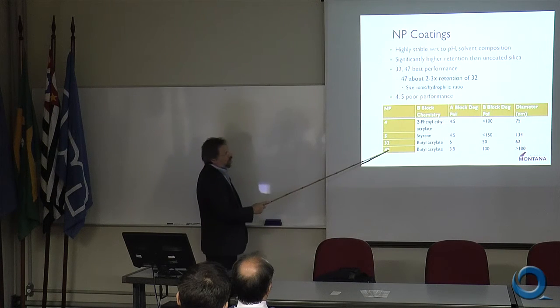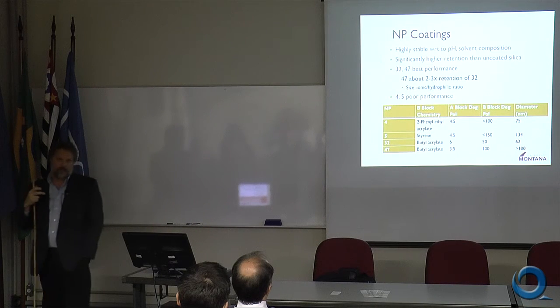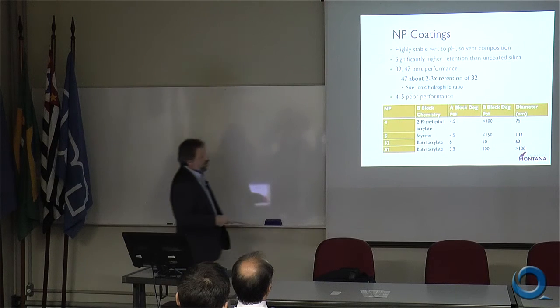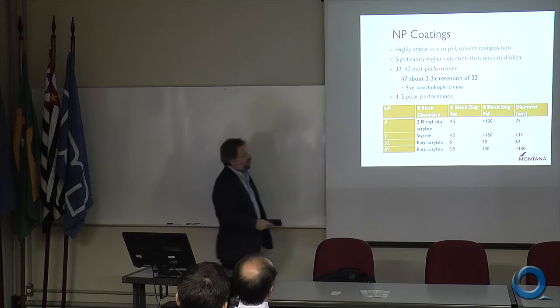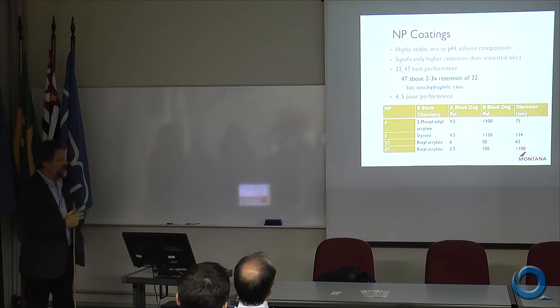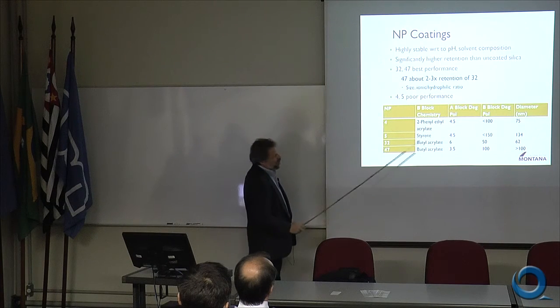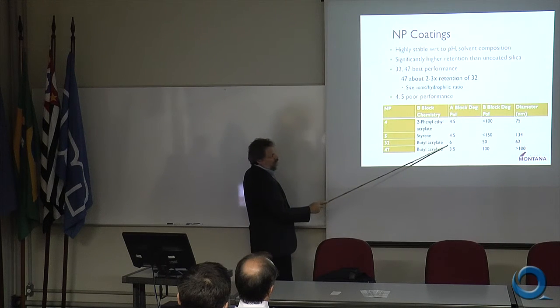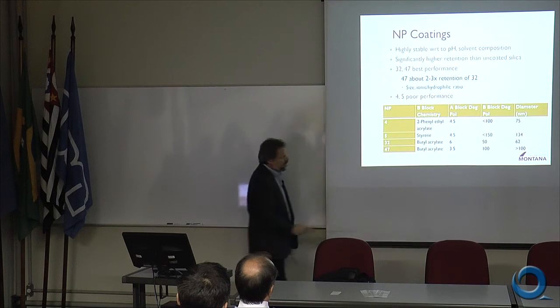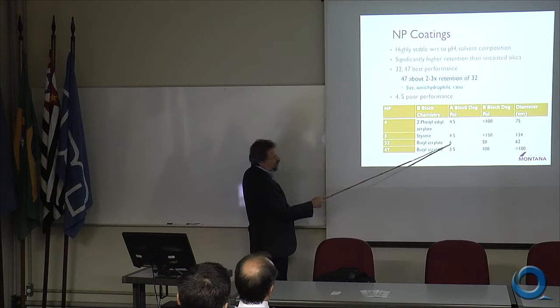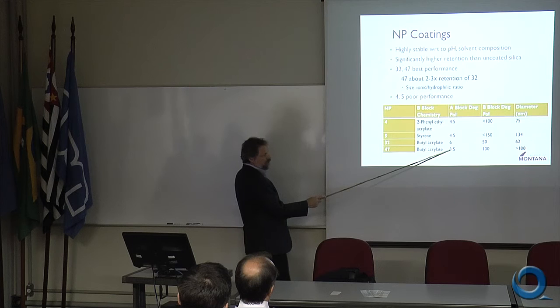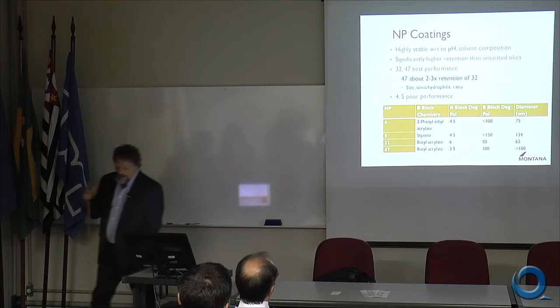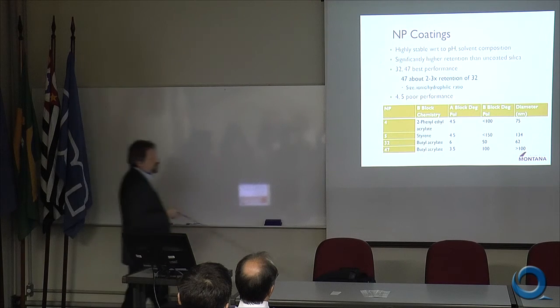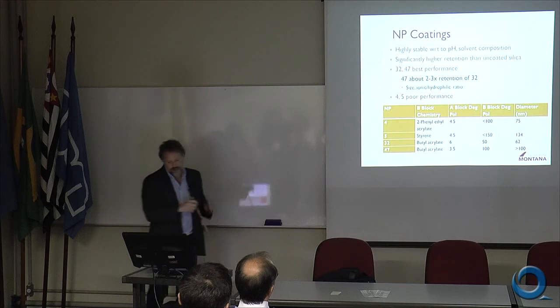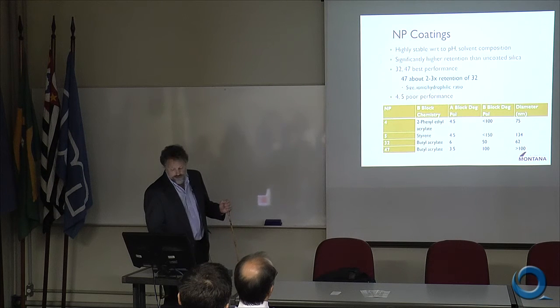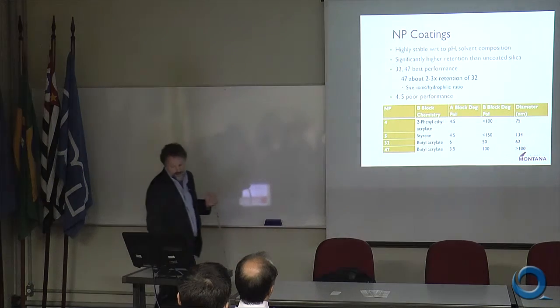And in general, nanoparticle 47 gave about 2 or 3 times as much retention or affinity for the analytes as did nanoparticle 32. And obviously this is very preliminary data. We don't have a lot of data to look at and to try to work out what's causing all of this. But the big differences between these are the ratio between the hydrophilic ionic block and the hydrophobic non-ionic block. Here we have a longer hydrophilic block and a shorter hydrophobic block. And here we have a shorter hydrophilic block and a longer hydrophobic block. So we're actually coating the surface with a more hydrophobic material with less ionic character, but still sufficient ionic character to allow the material to adsorb to the surface and remain there in a very stable form.